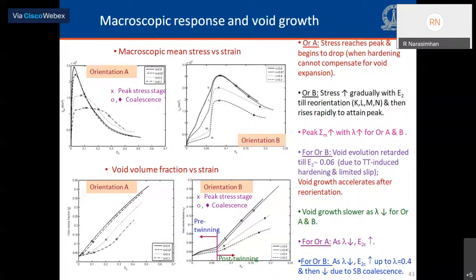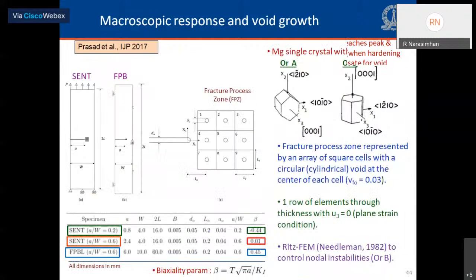And also the strain to coalescence in the case of orientation A increases as the stress ratio lambda decreases. Whereas in the case of orientation B, this happens up to lambda 0.4. And then between 0.4 and 0.2, there is an inverse effect with the strain to coalescence dropping. And this is because of the change in the coalescence mode, which I noted earlier.